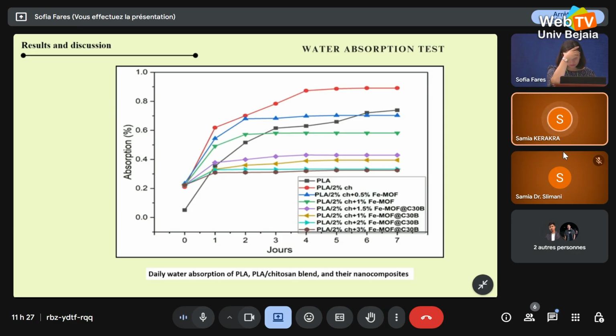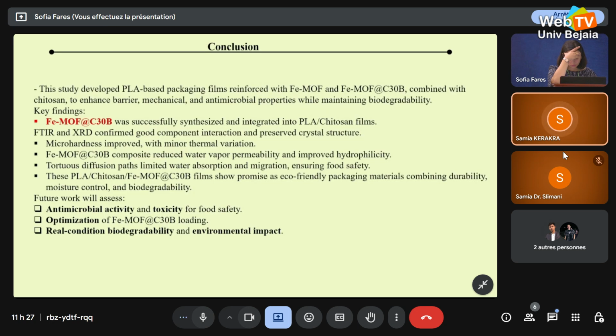As a conclusion, we can see that this study developed PLA-based packaging films reinforced with both MOF and MOF clay composites combined with chitosan, which can enhance barrier properties, mechanical and antimicrobial properties. We didn't put results here, but it really enhances even antimicrobial properties, while maintaining biodegradability. We are right now carrying out some biodegradability testing.